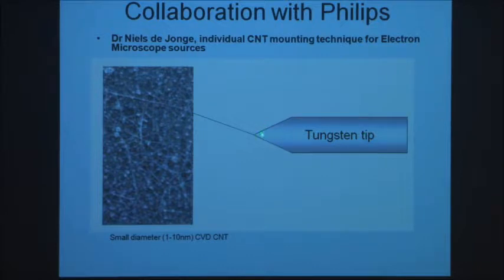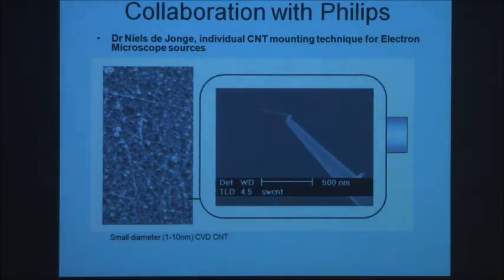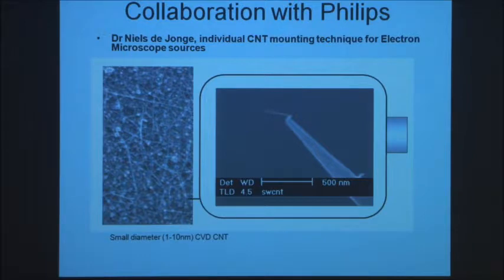You bring up a tungsten tip with a little bit of carbon glue on it. You stick it to a nanotube. And then, a bit like the IBM guys did with the metal nanotubes, you apply a high voltage and you blow the thing up. You end up with a nanotube attached to the tungsten tip, which we thought was very clever. The only problem is, when you do it n times, you find that maybe n minus 1 times you get this: the nanotube actually isn't aligned with the direction of the tip.